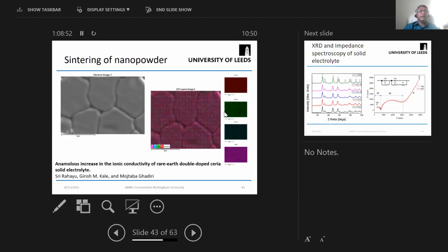Interestingly, the sintering temperatures, because they are nanopowders, is brought down quite significantly. We have been able to sinter these nanoparticles to full density, almost 98 to 99% of theoretical density, at about, I think, 1100 or 1200 degrees Celsius compared to the conventional sintering temperatures in excess of 1500 degrees Celsius. And you can see that the material is fully dense. These are the grain boundaries, and these are the grains, CGO co-doped with holmium grains.